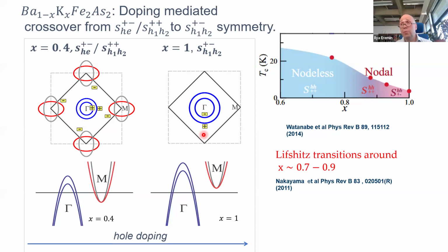However, there has been some experiment where they measured the number of dislocations in the crystal, and they cannot really account for the effect. So that still remains a puzzle. Superconductivity is two-component, breaks time reversal symmetry, but it's very likely not triplet.